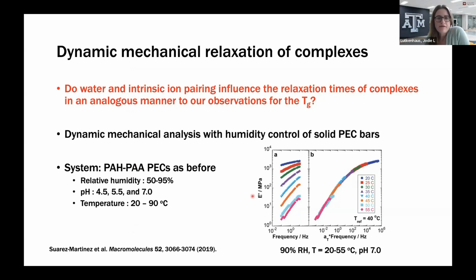Here's a plot of a PAH-PAA polyelectrolyte complex prepared at, I think this one is at pH 7, and we had gone through a series of temperatures and measured the frequency-dependent storage modulus at a certain relative humidity. So with that relative humidity, you know how much water is in there.